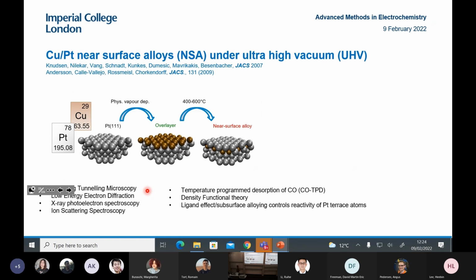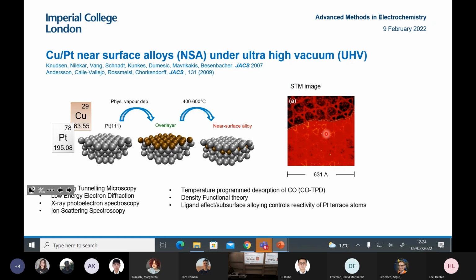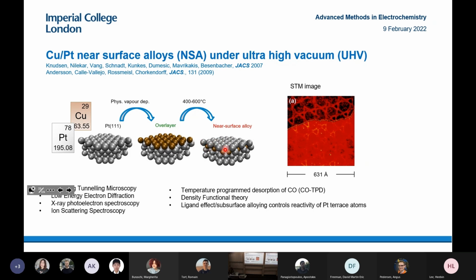But in my old research group, a lot of people have been using ultra-high vacuum surface science. They've been looking at the ligand effect. Essentially what they've been doing is making what's known as a near-surface alloy. They physically deposited a copper overlayer onto a platinum surface, and then they annealed it in ultra-high vacuum, and they found that they could make it more noble, more inert. They characterized it using a lot of methods, including STM, and they could get nice broad terraces and a very ordered surface when they did this. They found, for example, when they tried to react it with carbon monoxide, it interacted much more weakly with carbon monoxide than a pure platinum surface. And the top surface was platinum, and the copper was only in the second surface layer.